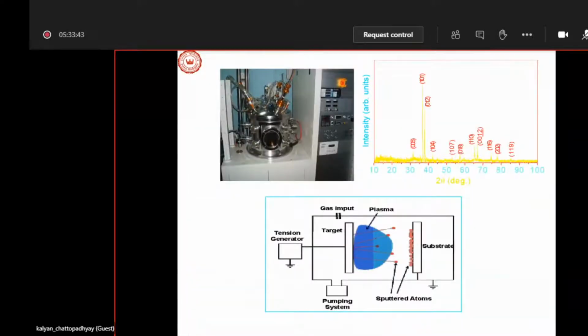When this was suggested, we also started working on this material for more than 2 decades. Initially, the phase formation was itself a challenge, because in this ternary system, maintaining the stoichiometry and correct phase formation was a challenge, and also the thin film fabrication. But we overcame all these problems, and this is a 3-target magnetron sputtering system in our lab. We also use RF magnetron sputtering. I am not discussing the technique, but the correct phase formation in thin film form has been achieved.